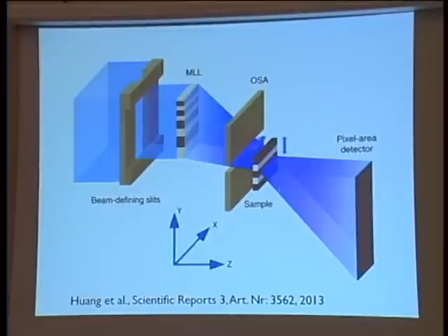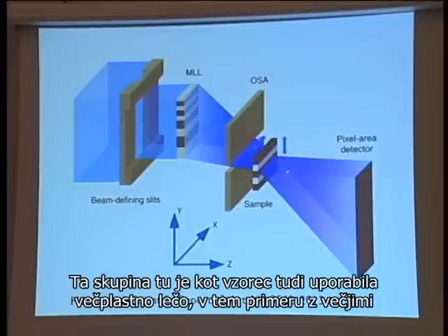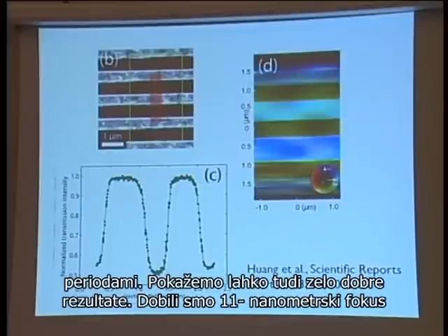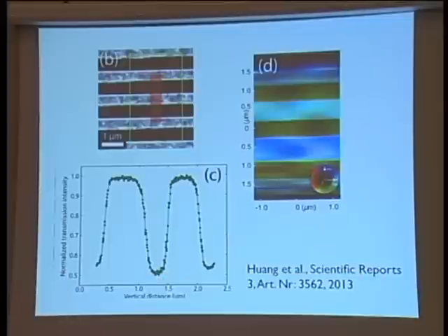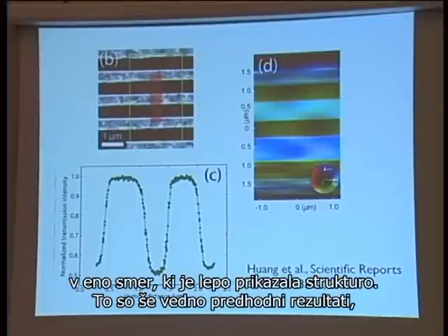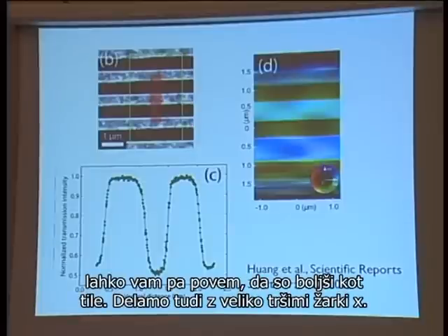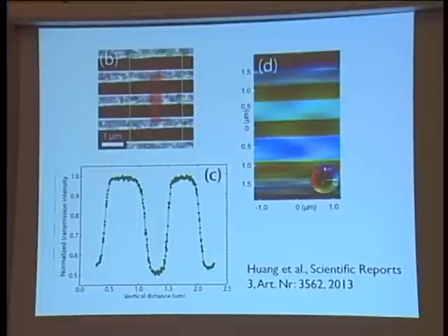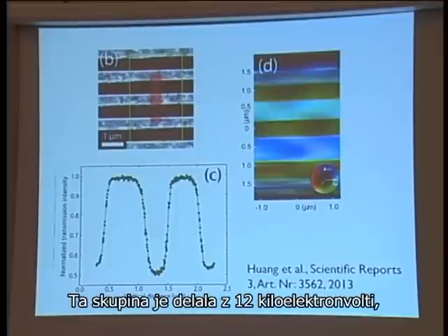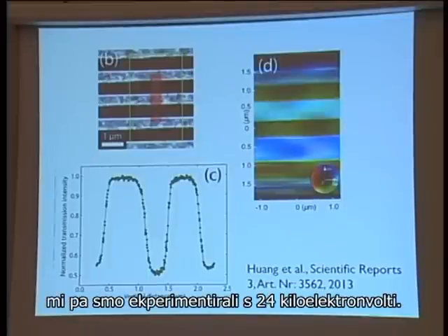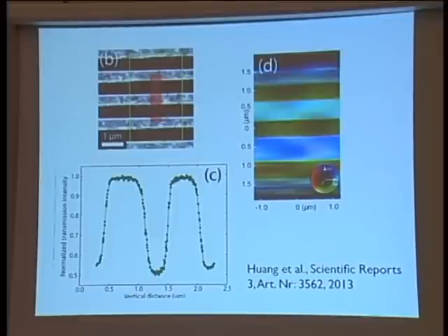And this group also used as a sample another multilayer with a larger period in this case. And they were able to demonstrate a very good result. They got an 11 nanometer focus in one direction and were nicely resolving the structure. Our results are still preliminary, but I can tell you that they are better than this. And we were also working with much harder X-rays. This group was working at 12 kiloelectron volts, and we were doing experiments at 24 kiloelectron volts.